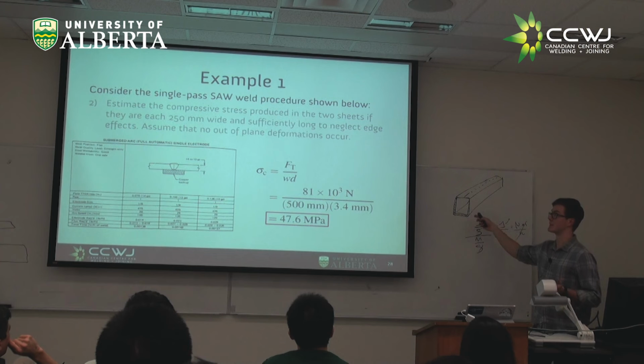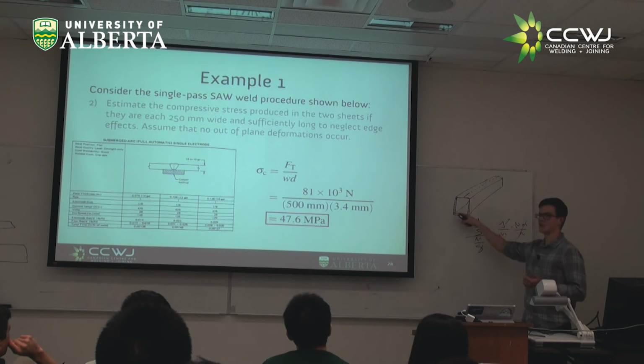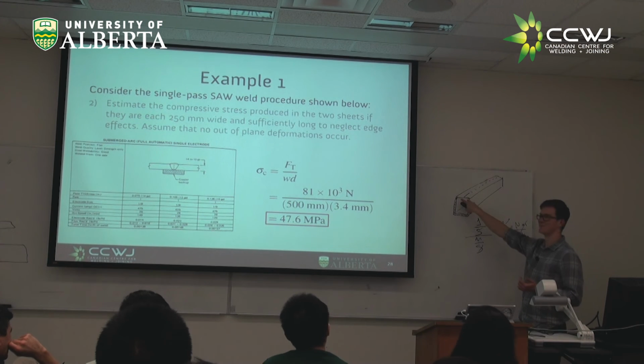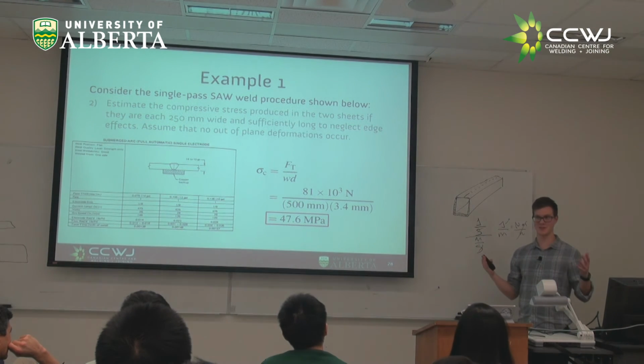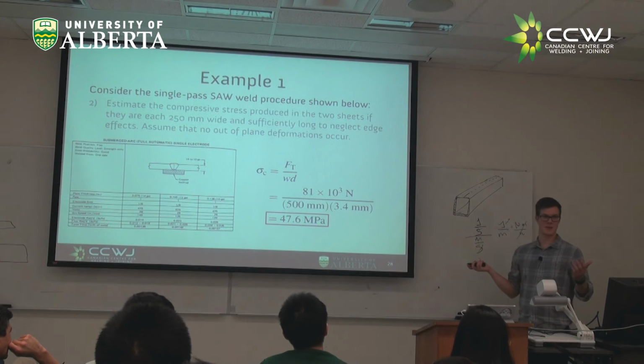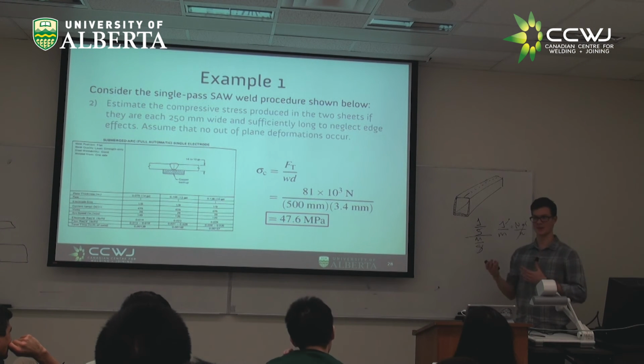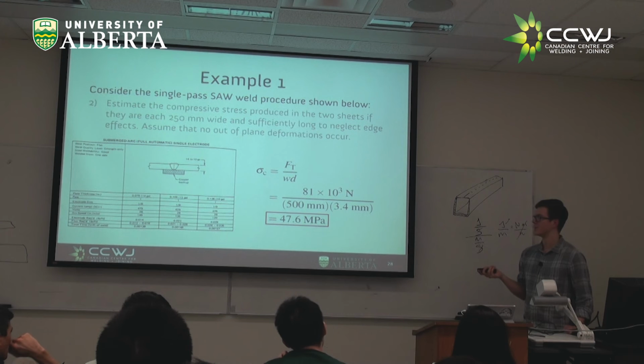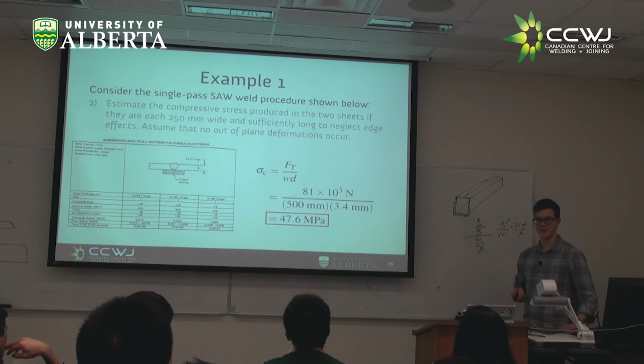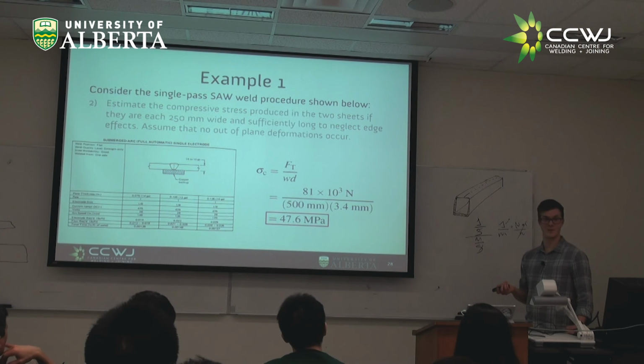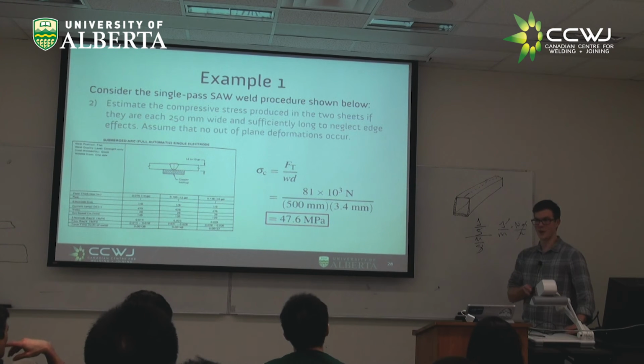Same thing if we're building a beam like this, and it's 250 millimeters on each side. We have 250 here, 250 here, 250 here, 250. We've now got 1,000 millimeters. We're twice as wide. This stress becomes half of that value just for the compressive stress, and our assumption gets even better. Same thing if we're dealing with even stronger materials. A36 is kind of one of the lowest strength structural steels you're going to encounter. It's only 250 megapascals. If you look at the plot from last class where we talked about 300W, 400W, 440W, all of those are significantly higher strength.